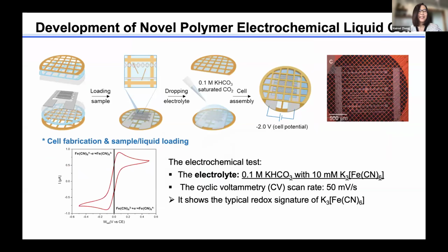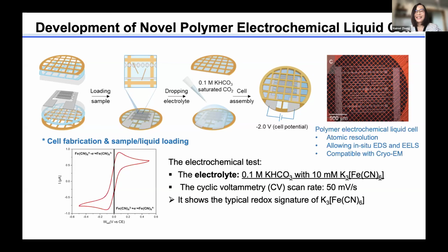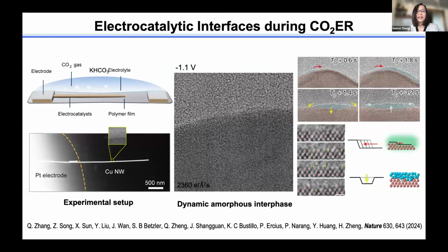Here I show very briefly the development of the polymer liquid cell. We put a polyimide membrane on this aluminum oxide insulated copper grid, and we put an interdigital electrode, and this shows classical electrochemical behavior. Then we can use this type of liquid cell to study high resolution electrochemical processes, really challenging electrocatalysis processes I will show, and it is also compatible with cryo-EM, so we can fast freeze the intermediate state without shattering the membrane.